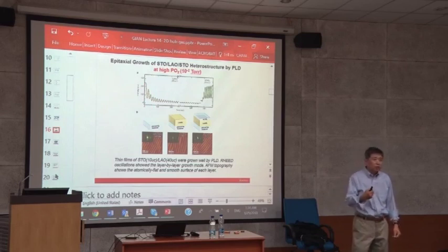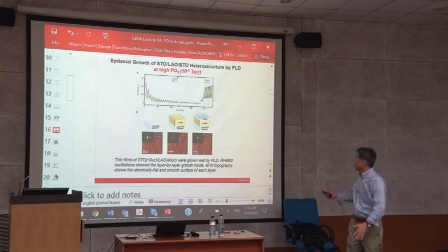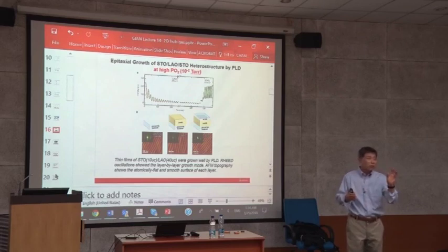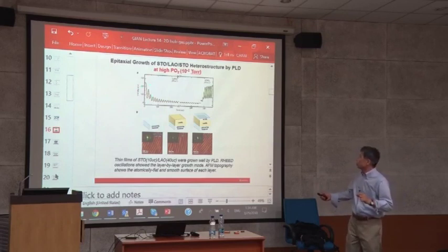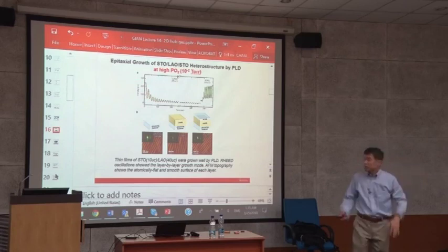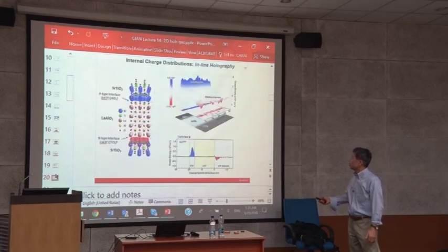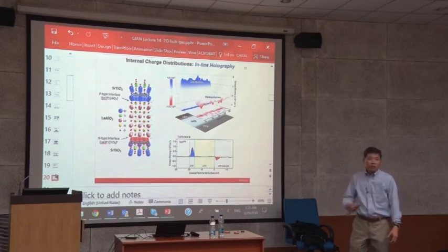You can calibrate this by reflectometry. Yesterday, remember I said you grow 100 oscillations, then afterwards you measure the reflectivity, and you get exactly the thickness, so we know exactly what one oscillation corresponds to. One oscillation is exactly one unit cell, we know that. So if you count the oscillations and stop here, that is the termination of one unit cell, a full coverage. But this coverage always happens as unit cell by unit cell growth, because this is the building block. Once you start with B termination, it ends up with B termination.